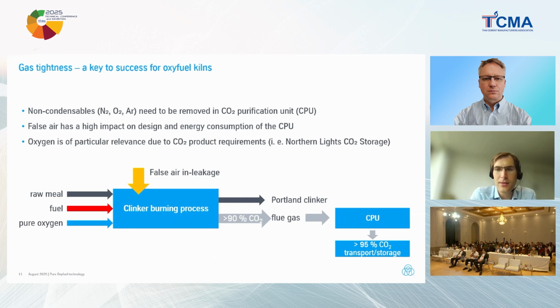At the end, CO2 purities way above 95% CO2 are required. For final products, even above 99%. And this means that the higher the CO2 concentration already is in the clinker burning flue gas, the more efficiently it can be purified. Especially the non-condensables are of particular relevance, mostly oxygen, because the final product often requires very strict limits regarding non-condensables, especially on oxygen. There are oxygen limits as low as 10 ppm in the final product. That also means that small fluctuations in the oxygen concentration in the clinker flue gas are already relevant regarding the CO2